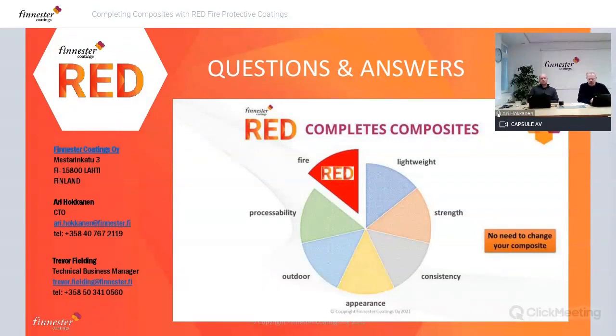How does the coating behave under abrasive forces? It has very good abrasion resistance compared to polyurethanes. Polyurethanes are kind of soft. These are hard but tough coatings. So the hybrid chemistry enables that combination from the organic inorganic world. So these are hard but tough, but not elastic. But they are more or less tough. So it has very nice abrasion resistance. We can give you, of course, more details. We have done tests, but we can go through them separately if you contact us later.